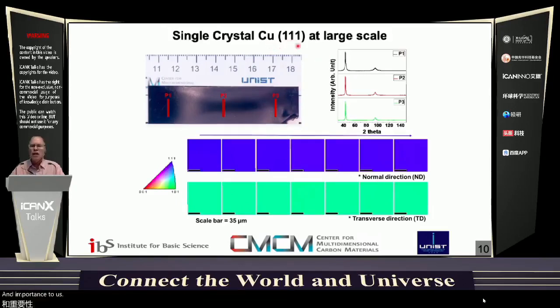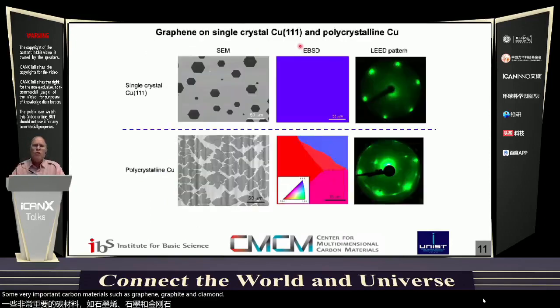And of importance to us is that copper 111 is lattice matched to some very important carbon materials such as graphene, graphite, and diamond. So if we grow on this single crystal surface, and we arrest or stop the growth before we have a continuous film, interrupting the growth, the nucleation occurs and these islands will grow. And you can see by eye, they look very closely aligned. In fact, they are. They're epitaxial with the copper 111 surface. And as they grow, they will actually join together very perfectly.